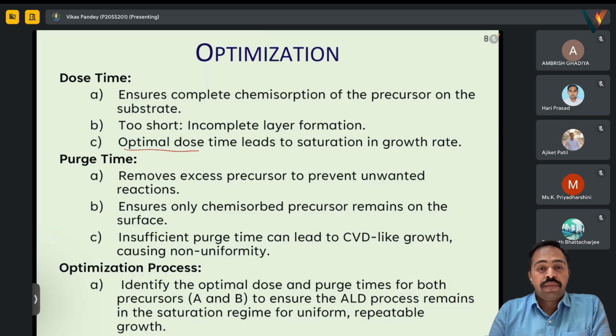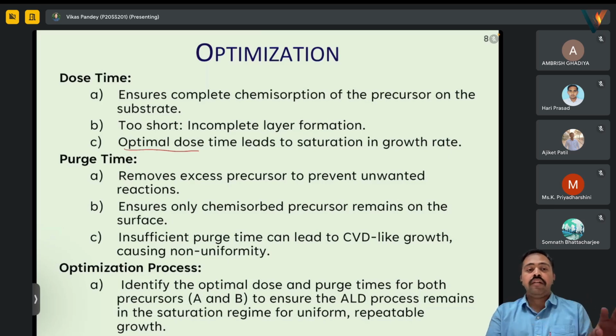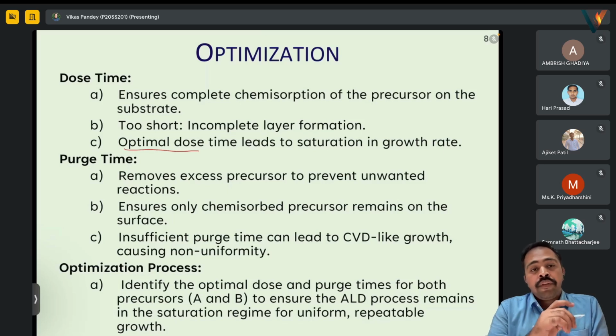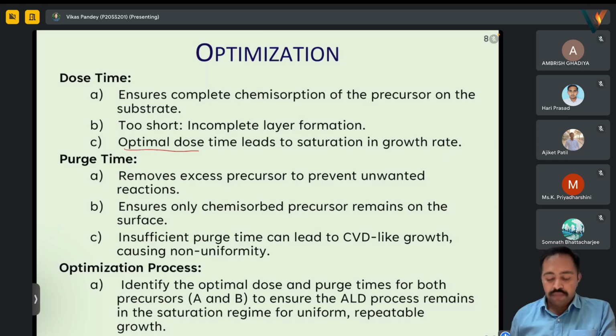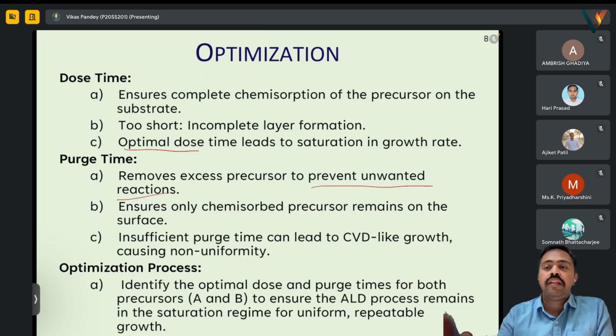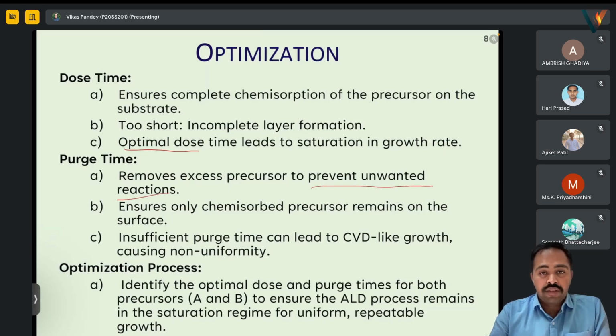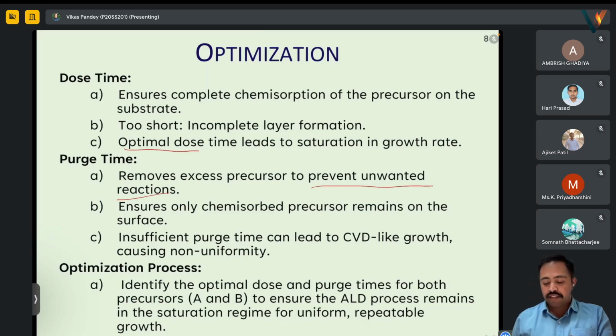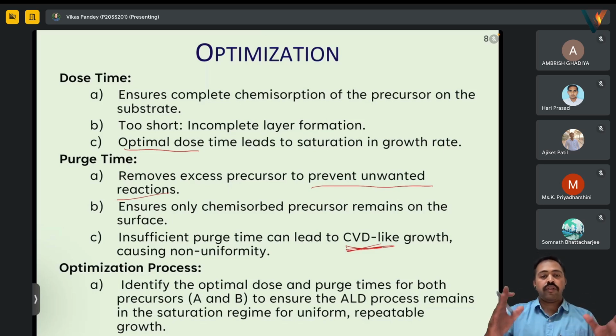Second is the purge time. If we have to remove the extra material, that time also is very critical. First, the purging should be for adequate time to remove anything that is extra. And if we are not removing this, it will be like CVD. A lot of reactions will be taking place, and we will not get the monolayer we want, and there will be no uniformity. So both dose time and purging time are very important.